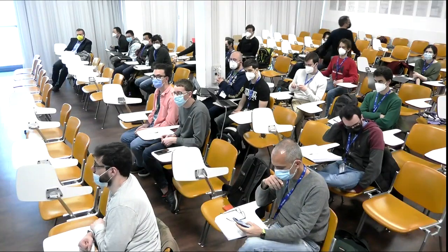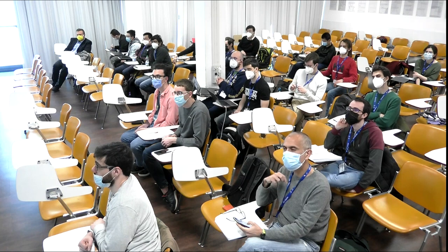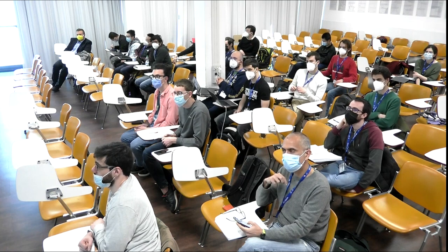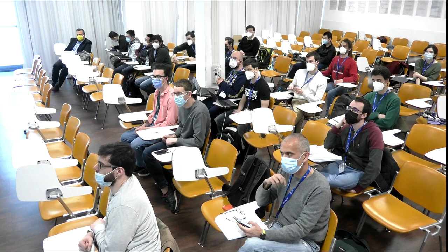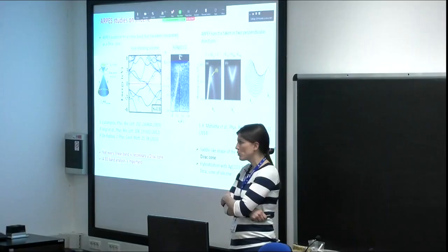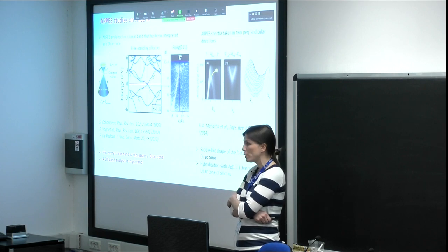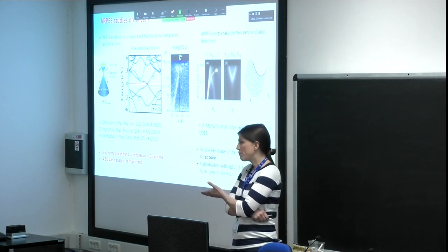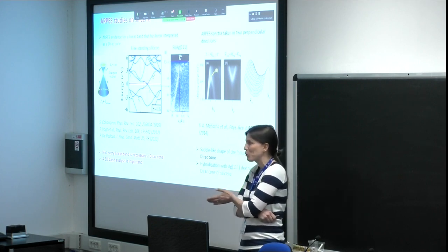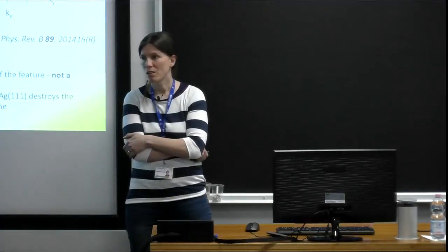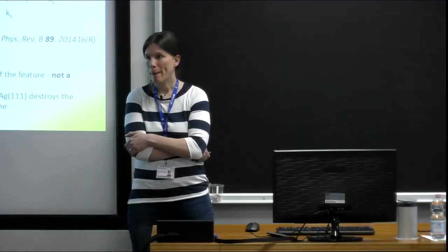And I think the example of silicene is nice, because I'm sure there was some theoretician who was ready to say, yes, this is exactly the band of silicene, I'm able to compute it and I get the same, but in the end it was the band of the substrate. As far as I remember, it also depended on the thickness of the slab one was using for the calculation. When one used a 5-layer slab, one showed a linear band, but these linear bands also come from silver itself. So the point is to pay attention not to jump directly to the conclusion. Okay, then we can start with the questions.